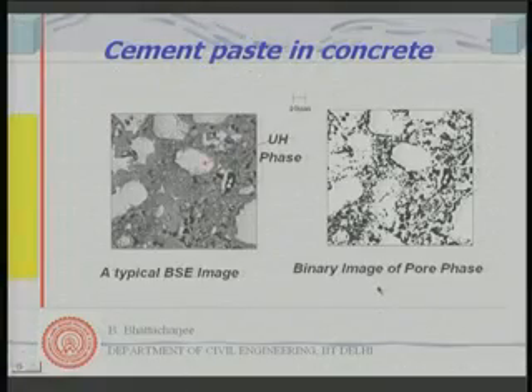Now, if I look at this backscattered electron image of cement paste in concrete, this is how it would look. From the places where electrons do not scatter back, they will look black. In a backscattered electron microscopy image, the black ones are the pores, the white ones are the unhydrated phase. The reflection in a gray image depends upon how much scattering. There are equations of physics which tell us that the unhydrated phase gives us white color. Gray color of this kind is the hydrated phase, and the black ones are the pores.